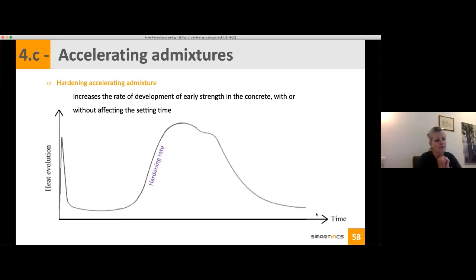And then you can have an effect over your hardening rate, and this is hardening accelerating admixture. It will increase the rate of development of the early strengths in your concrete. And this can be together with affecting your setting time or not. So you can have both. You can reduce your dormant period and at the same time increase your hardening rate. Or you have the same dormant period, your initial set will start at the same time, but the hardening will go much faster than your control mix. So what you will see here is that the slope will be steeper. So this is hardening accelerating admixture.